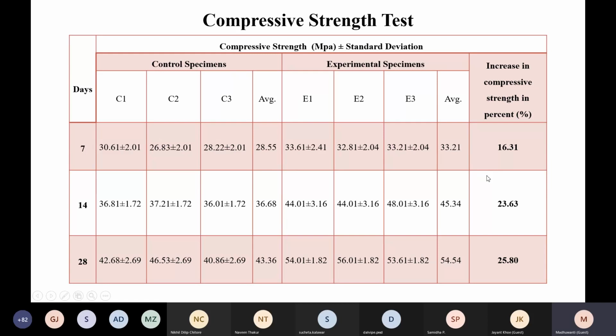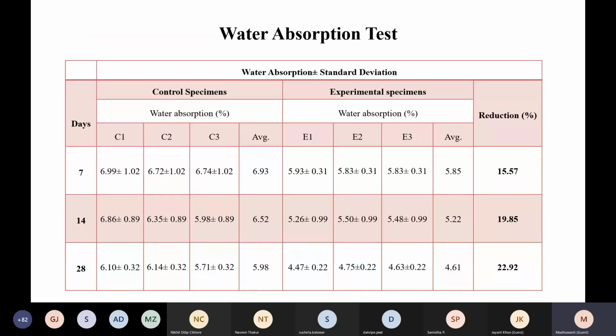So as you can see that on the 7th day, the increase in compressive strength in percent was 16.31 of experimental as compared to control. On 14th day, the compressive strength was increased by 23.63% of experimental as against the control. And on the 28th day, the compressive strength of experimental specimens was increased by 25.8% as compared to control.